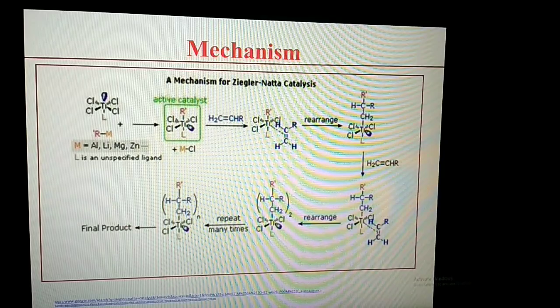Now the mechanism — this is very important. In the mechanism of the Ziegler-Natta catalyst, the starting material is TiCl4, which has Cl ligands, one vacant coordination site, and L represents the unspecified ligand. In the presence of trialkylaluminium, here designated as R-M, where M means aluminium and R is the alkyl group, such as ethyl (C2H5).